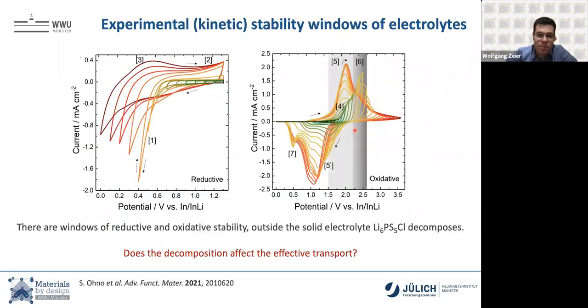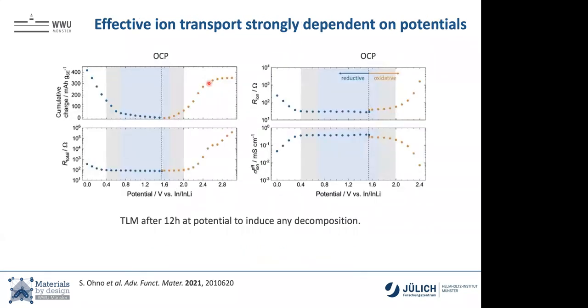And what one can do is run stepwise CV, where we increase the reversal potential by 0.1 volt, go back and so on. And once we see a lot of current increase and additional features showing up, we know that our electrolyte is decomposed. And we can do this oxidative. Green means it's stable. Down here in the reductive regime, green means it's also stable. So the decomposition range that we're in, or the stability window, is actually a little bit larger than the thermodynamic one. So the kinetic stability in the end. But the question is, does this affect our transport?